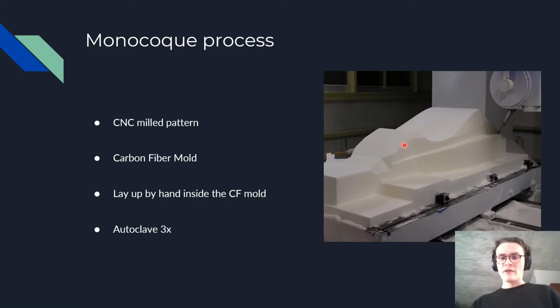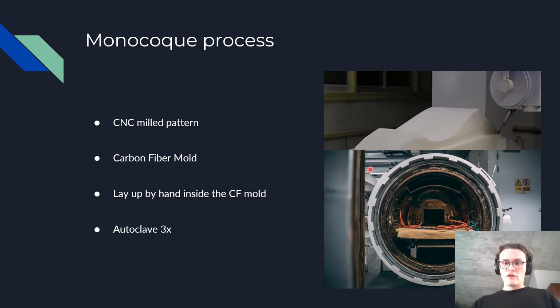I already mentioned why. And so when laying up the carbon fiber on the inside, after placing those first 10 layers or so, whatever they have come up with in their layup schedule, it goes into the autoclave. Of course, the teams have very modern autoclaves just to get that extra bit of performance out of the part. After going through the first curing cycle, they take out the part and then attach the aluminum honeycomb.